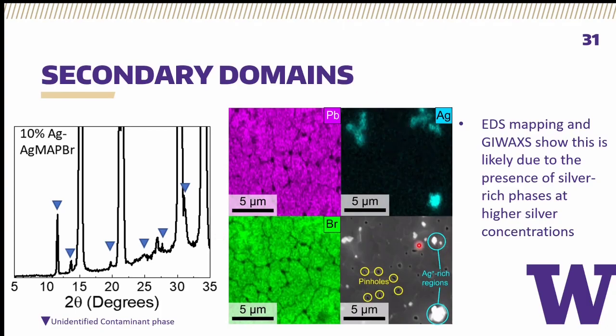They're rich in silver. You can see them differently in the contrast in even bare SEM. And you can even do crystallography on them and see their peaks in X-ray diffraction or grazing incidence wide angle X-ray scattering as well. Unfortunately, we aren't able to identify this material based solely on X-ray scattering. There are no peaks in the crystallography database that correspond to these different peaks that emerge in our GIWAXS patterns. And furthermore, we weren't able to, either through solid state or solution phase synthesis methods, generate bulk thin films or powders of this impurity phase. And so we weren't able to fully characterize it.